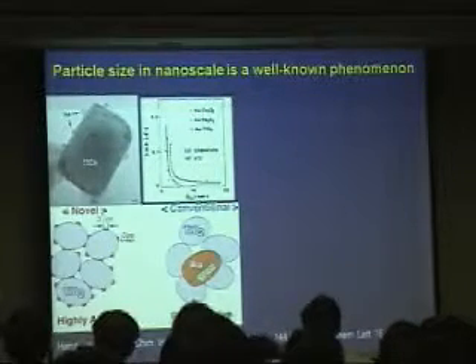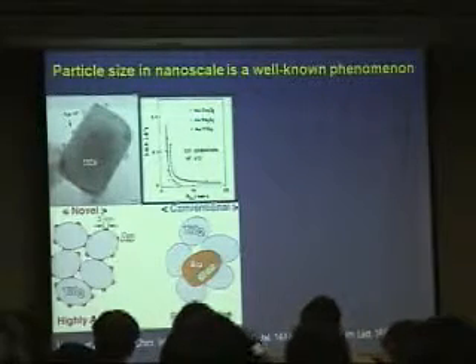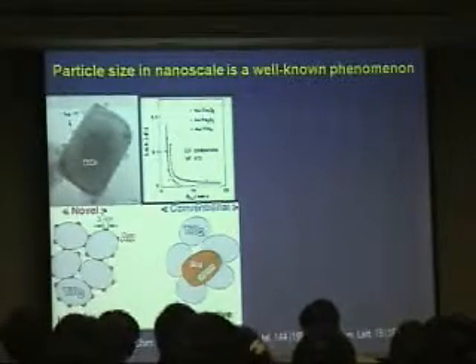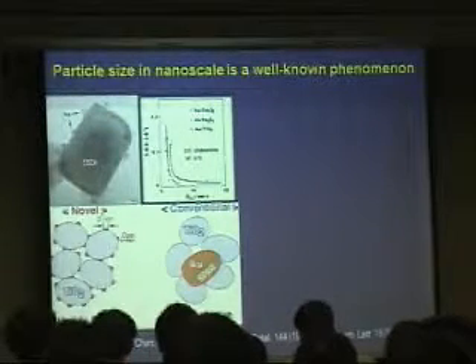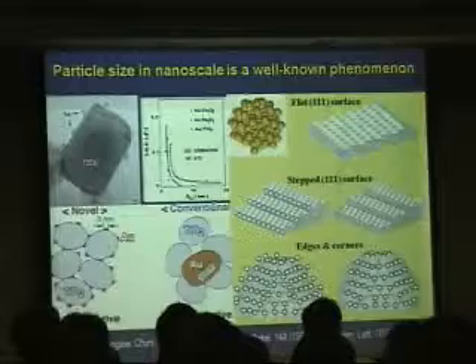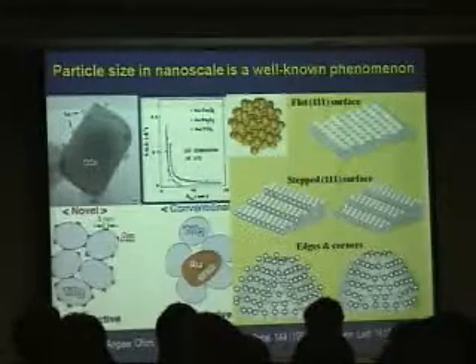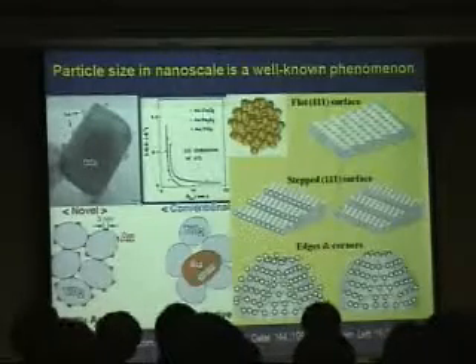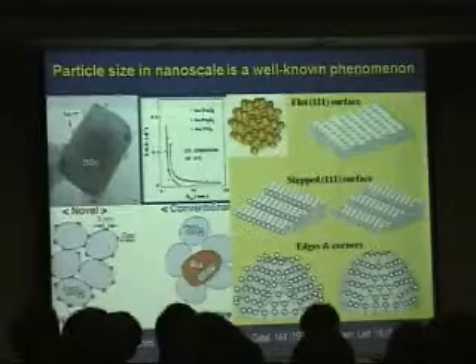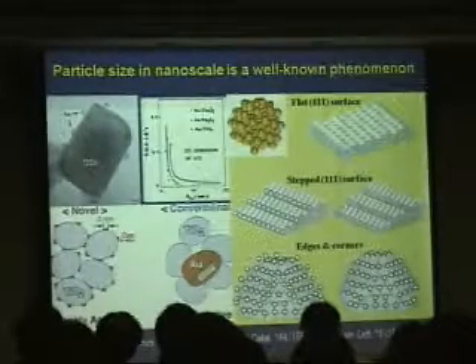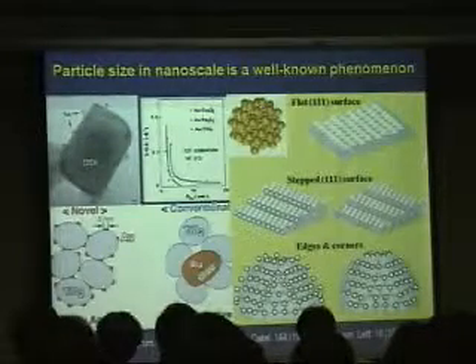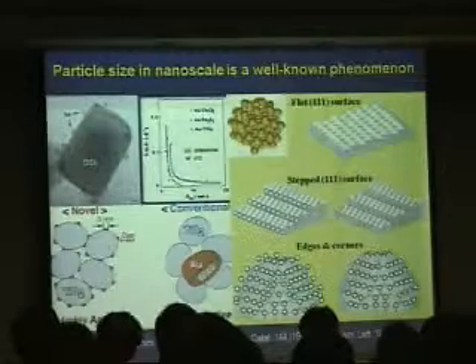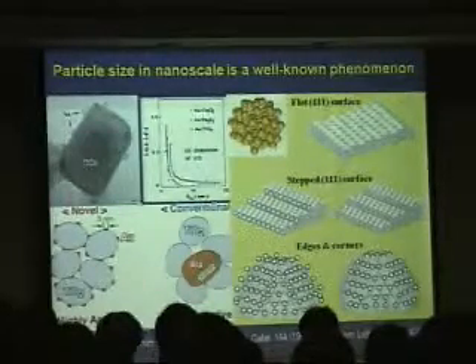Many people have worked from the very beginning to control the size. At a very small particle size, they can adjust the active sites of the catalyst. This is a typical example from Professor Masatake Haruta from Japan. He studied gold nanocatalysis. This is a well-known story, and the crystal size is 2 to 3 nanometers. The reason is that with decreased size, the active sites are largely increased. These so-called active sites are actually represented by the surface atoms, whose coordination number is much lower than normal, making them more active for the reaction. That is the intrinsic reason why decreasing the size increases the catalytic activity.